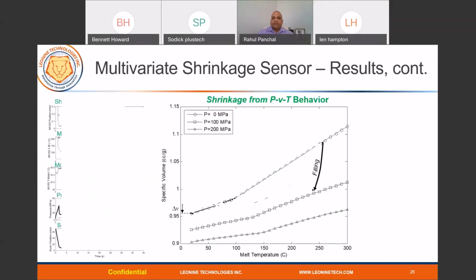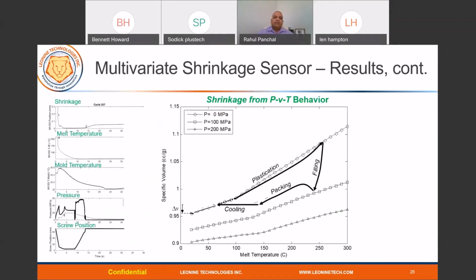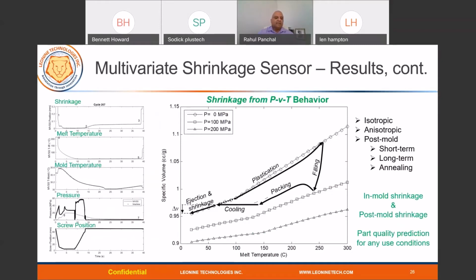And you can achieve the multidimensional analysis. First of all, you can create the entire PVT cycle for any injection molding cycle, and based on that PVT you can also estimate the isotropic and anisotropic in-mold shrinkage as well as the post-mold shrinkage, and you can use both for part quality prediction for any use condition. If you are going to use a part at 40 degrees centigrade and 60% relative humidity or at ambient pressure, you can estimate it. So if you want to create a worst-case scenario for your functionality verification for any product or part, you can do that.